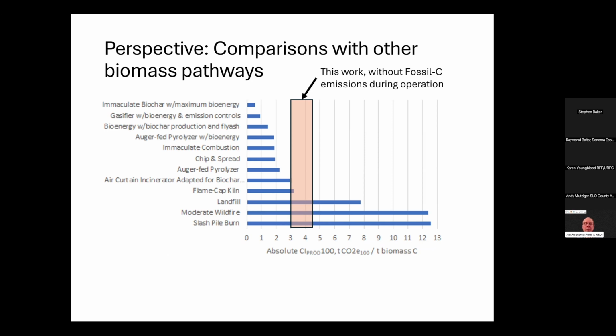We're about half the emissions you get if you were to landfill these same materials. And then we're lower than a lot of the higher tech biochar production systems. The best you can do might be down around 1 or so, if you've got all the bioenergy and emission controls and everything. But we're pretty much about where I expect us to be, somewhere in this range.